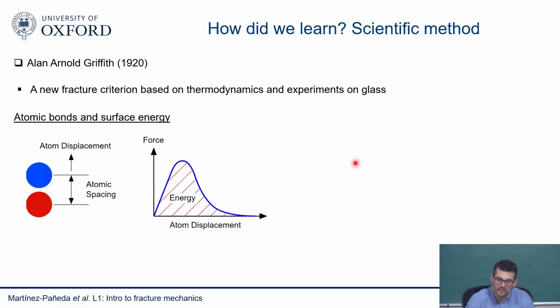So he basically conducted some experiments in glass, and he adopted an atomistic perspective where he said, okay, if I look at two atoms, then I know that I can plot the force versus the separation of those atoms, and it looks something like this. So you apply a force, and then you have a displacement in the atoms. Initially, those atoms are in some sort of equilibrium. It takes a lot of effort to separate them. But then eventually, when you reach a critical point, separating them becomes much easier. And at some point, the bond strength is broken, and therefore those atoms are free to go apart. That's the idea.